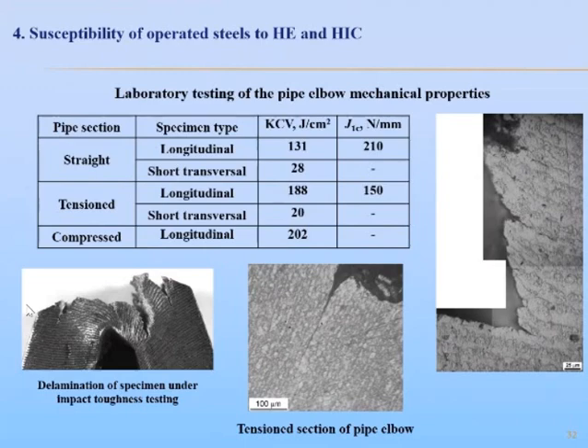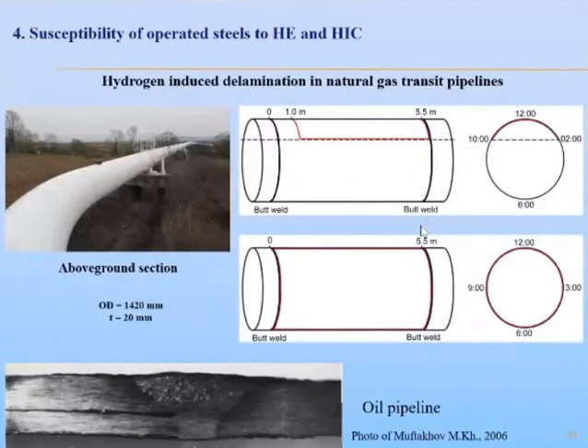Another case of the extensive delamination of pipe steel was detected on two sections of the above ground natural gas transit pipeline crossing a river. So two cases were revealed. The first one, only the upper part of the above ground pipe characterized by delamination, almost from one butt weld to another one. Another example of a full delamination between two butt welds was observed.